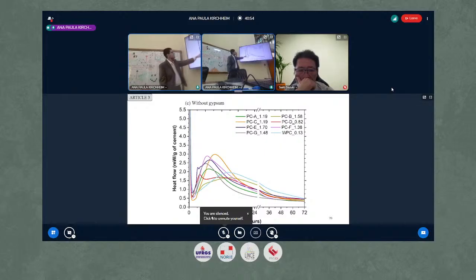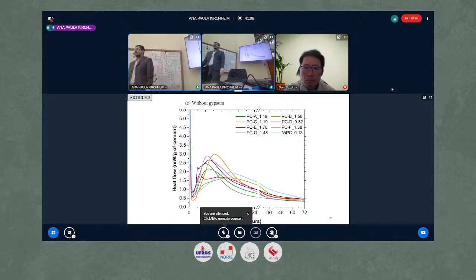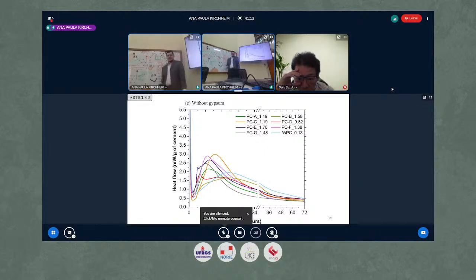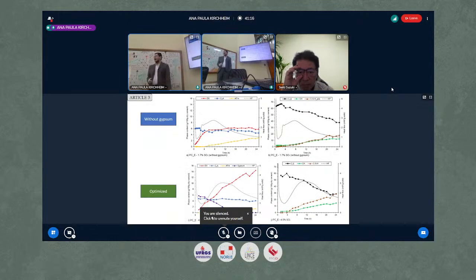But here we see that the sulfates are taking part, because we have here an aluminate peak 4 or 5 hours after the beginning of the hydration. So the sulfate in clinker is participating in the reaction. If you don't believe me, I ran XRD analysis, and we saw here, indeed, it's forming ettringite when we don't have gypsum. So ettringite is using the sulfate coming from the clinker. So the sulfate in clinker indeed participated in the aluminate sulfate reaction.